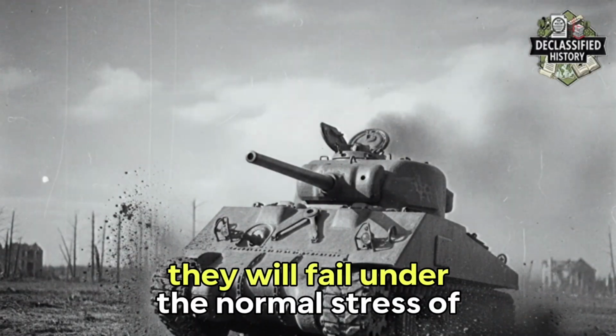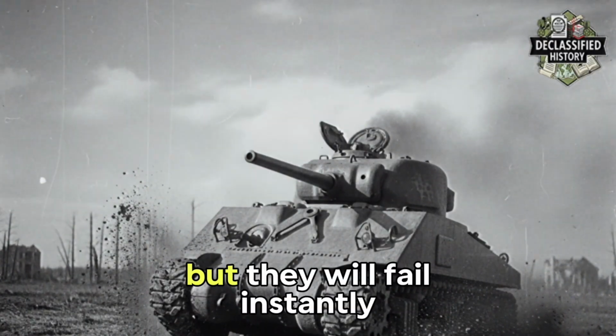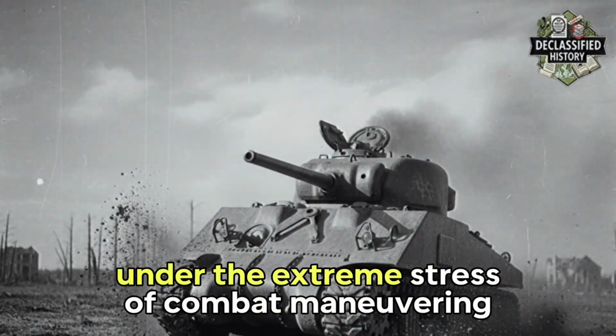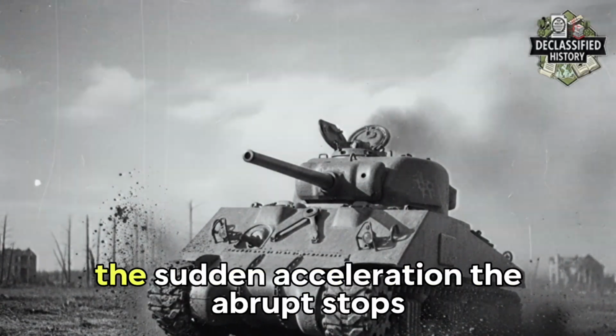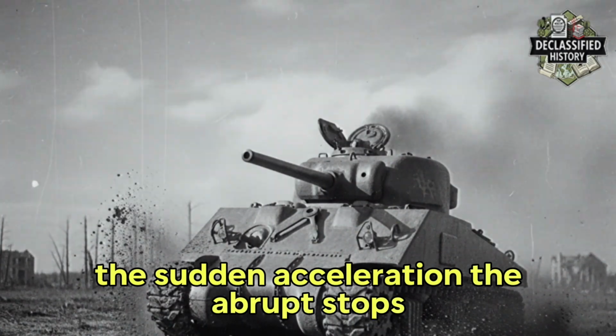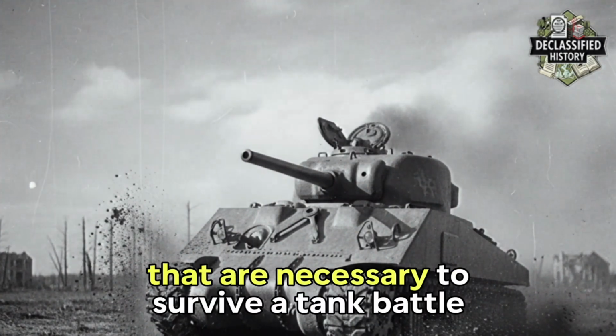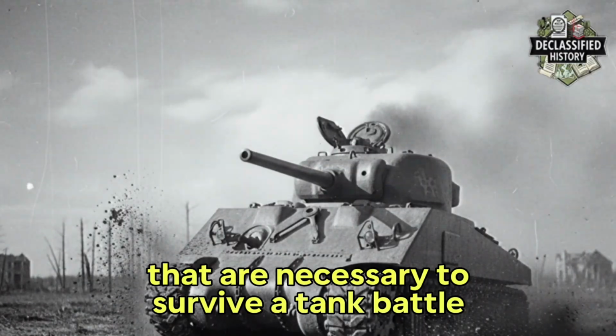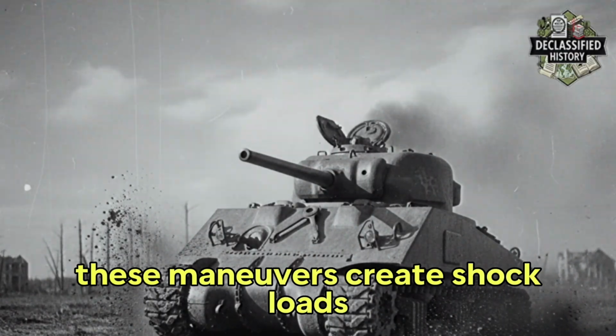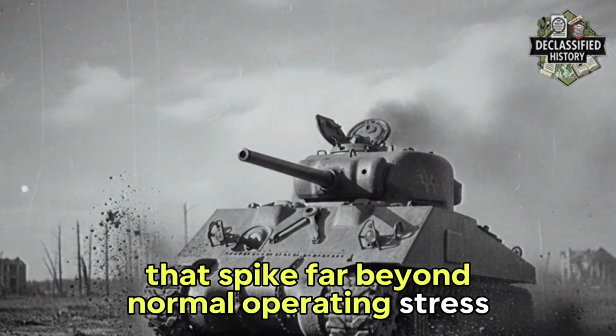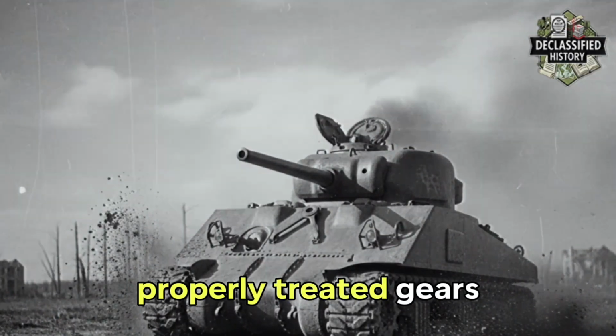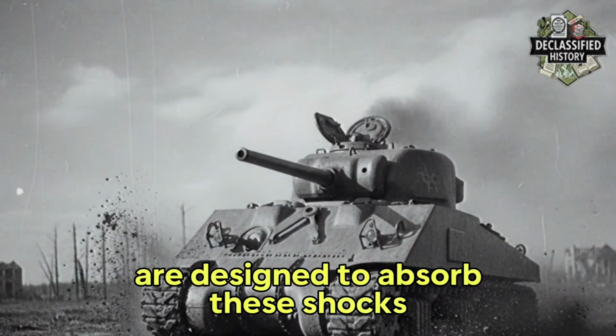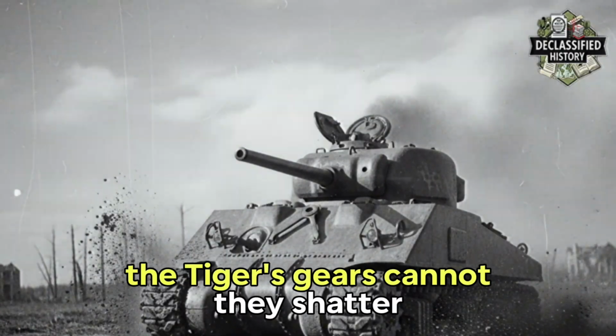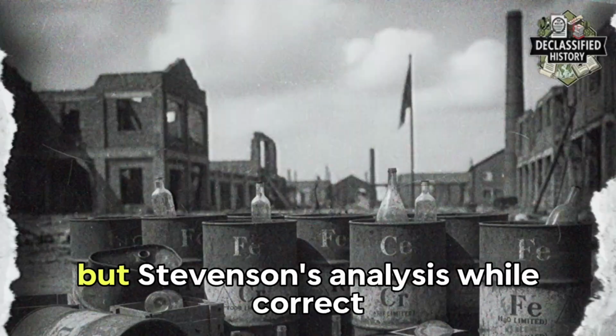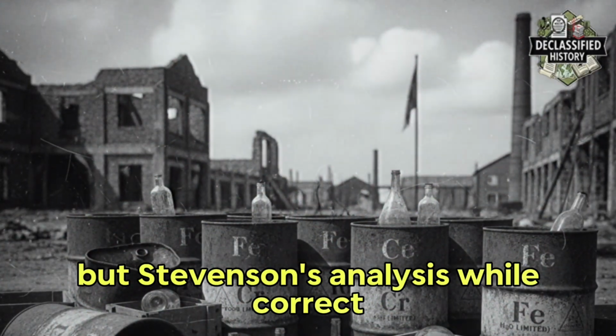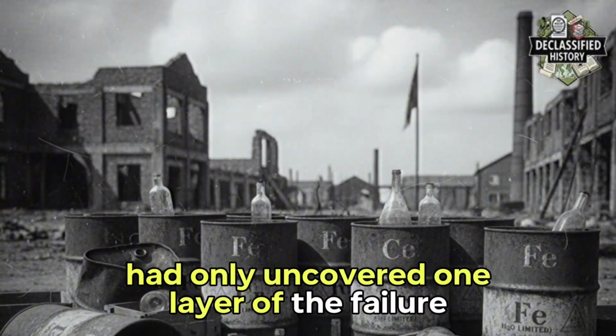They will fail under the normal stress of operation, but they will fail instantly under the extreme stress of combat maneuvering, the sudden acceleration, the abrupt stops, and the sharp skidding turns that are necessary to survive a tank battle. These maneuvers create shock loads that spike far beyond normal operating stress. Properly treated gears are designed to absorb these shocks. The Tiger's gears cannot. They shatter. But Stevenson's analysis, while correct, had only uncovered one layer of the failure.